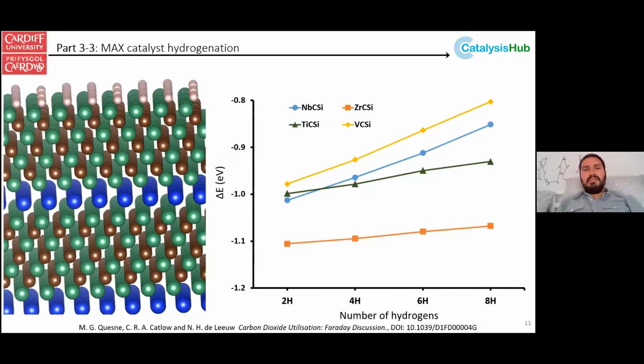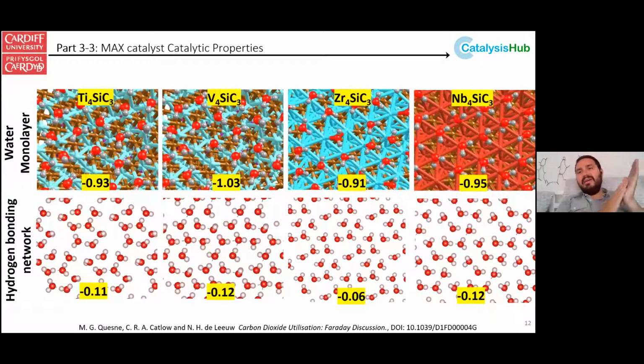But then we thought, okay, these surfaces are very, very highly reactive. And in an oxidative environment, what would happen to these surfaces? So maybe the pristine surface is not what we want to be looking at. So first we started by looking at forming a water monolayer. We tried a few different hydrogen bonding networks and found the most stable conformations.